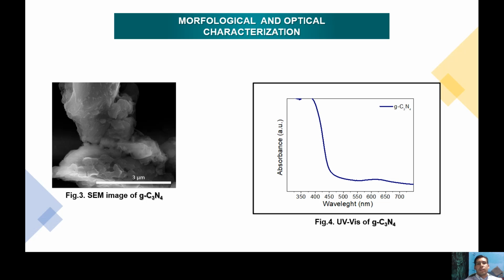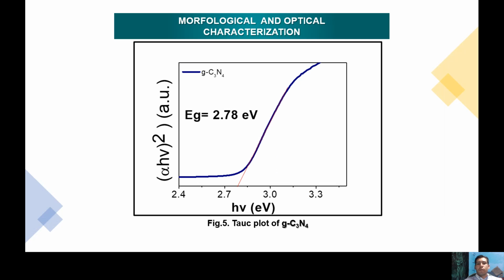As morphological and optical characterization, in figure 3, SEM image of the C3N4, we can see the characteristic shape of the C3N4 when we synthesize this material with the melamine precursor. And also in figure 4, we can see the UV-vis spectrum of the C3N4, and we can find this material has activity in the visible region. And with these values, we made a Tauc plot of the C3N4, and we can find the band gap. This is equal to 2.78 electron volt. This is characteristic of the C3N4, and this is characteristic of a semiconductor material.